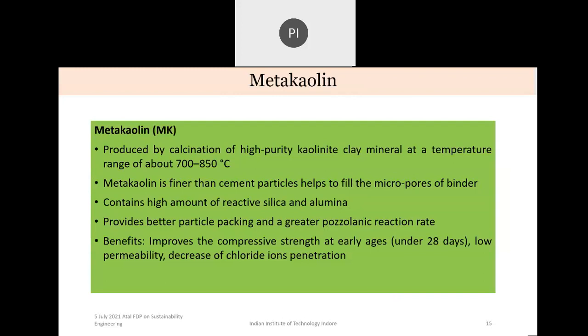Another recently popular material on which people have started working, and which is in fact the future of the cement industry, is metakaolin. It's produced by calcination of high purity kaolinite clay mineral at a temperature range of about 700 to 850 degrees centigrade. It is finer than cement particles and it helps to fill the micropores of the binder. It contains a high amount of reactive silica and alumina. It provides better particle packing and a greater pozzolanic reaction rate. Benefit: it improves the compressive strength at early ages. It leads to low permeability and it decreases the chloride ion penetration.